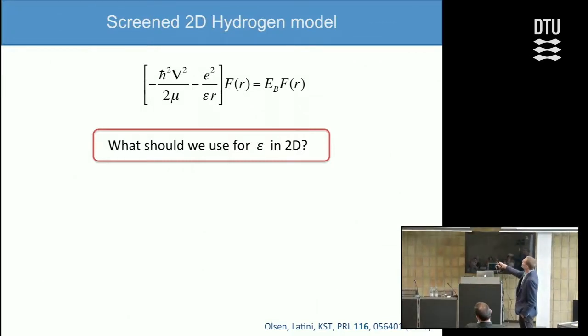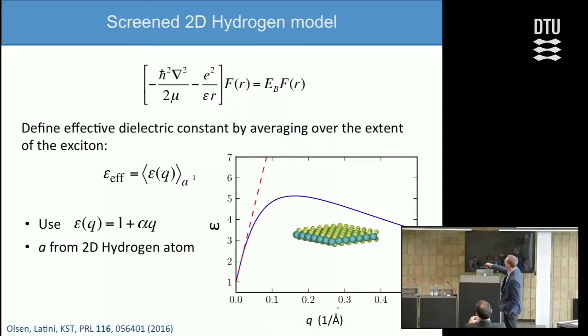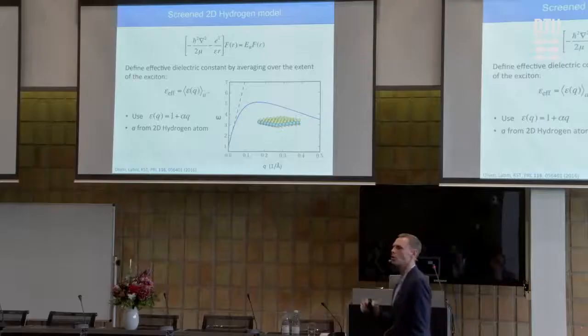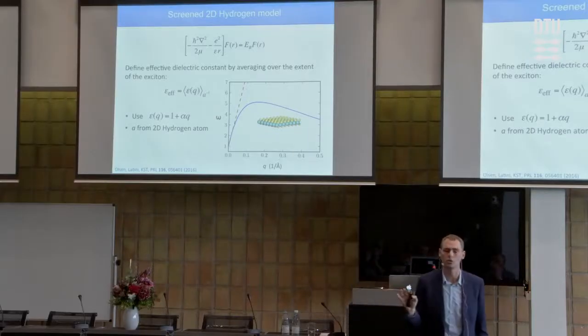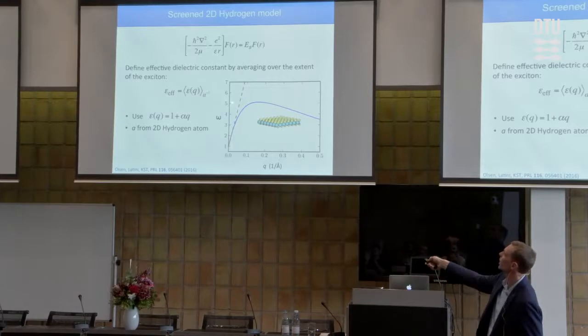So the starting point is this hydrogen model now in 2 dimensions rather than 3 dimensions, and we have this screening constant down here. So what to use for that? The problem is that depends strongly on Q, which goes to 1 here. So for Q going to 0, there is no screening at all in a two-dimensional material. So we can't just use a dielectric constant.